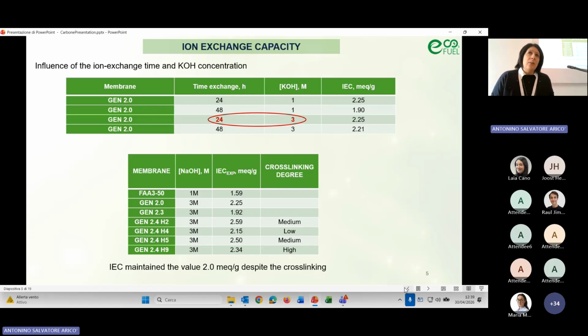Then regarding the contamination, it is not reported here, but we also performed the anion exchange capacity in chloride form. And in the titration of chloride, we generally reached the nominal amount. So in this case, we have a good accordance between titration in OH and titration of chlorides. So we believe that this is the full anion exchange capacity that we can reach.